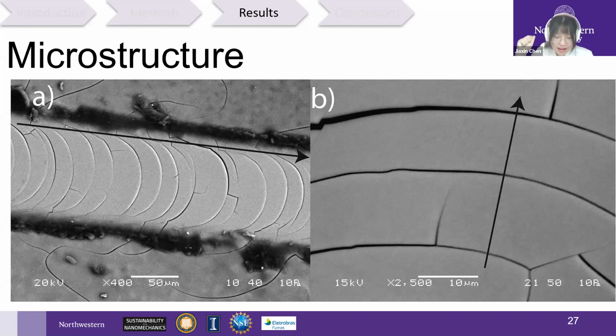When we zoom in, here comes the most interesting part. We observe curved cracks, regularly spaced and perpendicular to the direction of testing. The arrow represents the direction of the testing. At a higher magnification level, newly created fracture surfaces can be seen on the right-hand side figure. The presence of these fracture points points towards the predominance of fracture dissipation and motivates the fracture analysis of our test data.